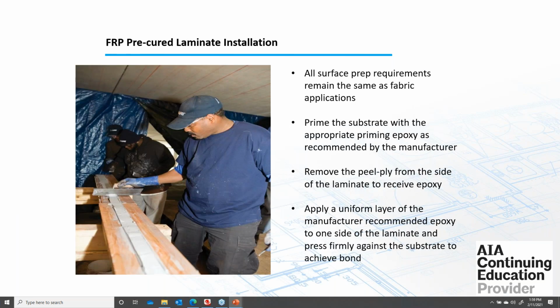Next slide. For the FRP precured laminate installation, or the CFRP plates, the surface preparation requirements remain the same as fabric applications. Then we still have to prime the substrate as recommended by the manufacturer. Then remove the peel ply from the side of the laminate to receive the epoxy, and apply a uniform layer of the epoxy adhesive to one side of the laminate.